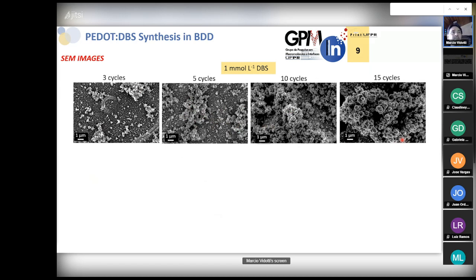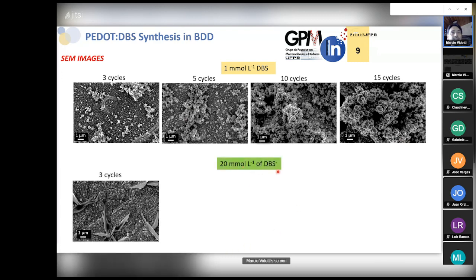We have done the very same study for the 20 millimolar of DBS, which is above the CMC, and we see that for 3 cycles, instead of observing this kind of aggregates, we observe a thin film layer and the presence of those structures here, which are not observed in the literature so far. Because when you use DBS above the CMC, normally you observe some round structures, but in this case, they are kind of flat, more similar to a leaf. And it's very surprising for us to observe this kind of structure.